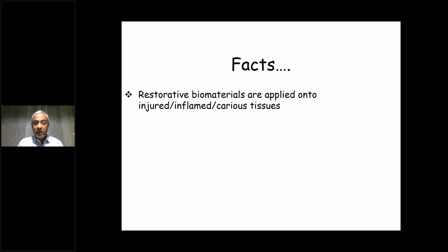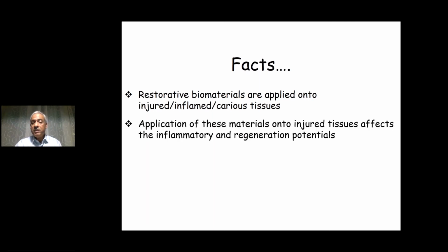Now, let me bring you back to the fact that restorative materials are applied onto injured and inflamed carious tissues, and the application onto these tissues affects the inflammatory and regeneration potentials. And I will show you the effects on the initial steps. This is particularly true in the pulp, which is located within inextensible and rigid dentinal walls. Because when you have inflammation on the skin, it's not too important that the skin swells, even if it swells too much. But if the pulp swells too much, that means tissue necrosis for the pulp.